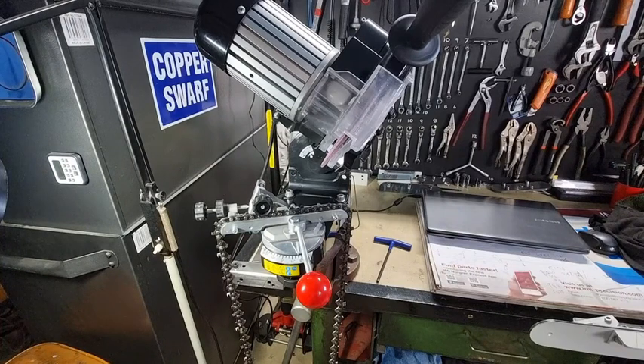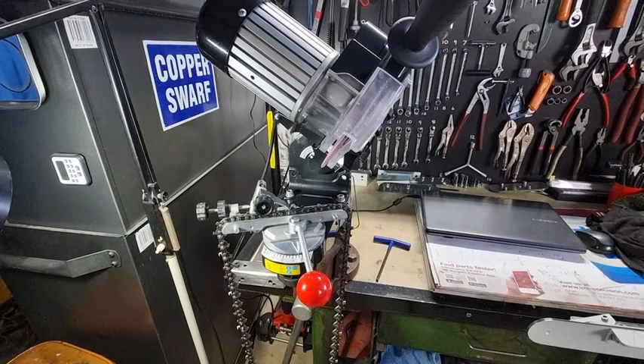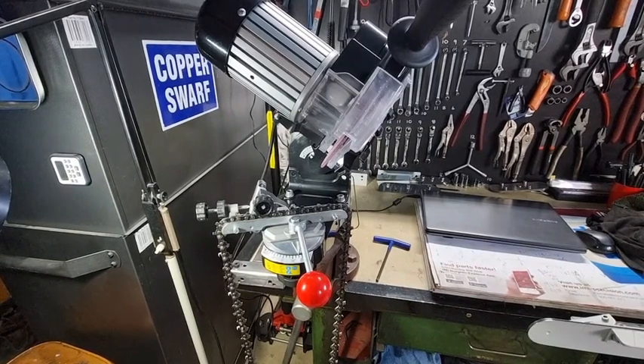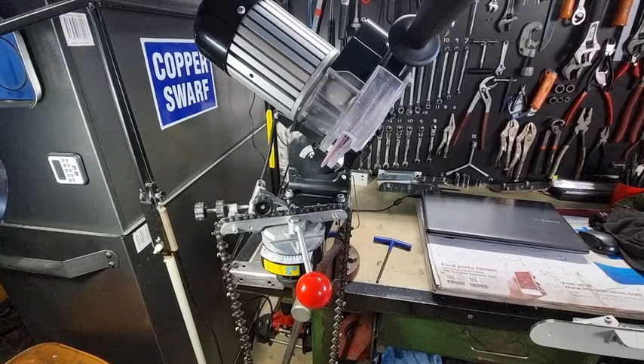So what happens to metal when you heat it up at lower temperatures? You start to get discoloration, and that can happen with a chainsaw grinder. Once you get to around 170, 180 degrees, you start to get a very light yellow colour. As you go up in temperature, by about 260 degrees it'll go brown, then at about 280 degrees it'll go purple, till you reach blue at 310. So your chainsaw teeth will case harden a few thou if you're using the grinder and you're getting it light blue. That's something you want to avoid. You don't want to be bluing the metal.